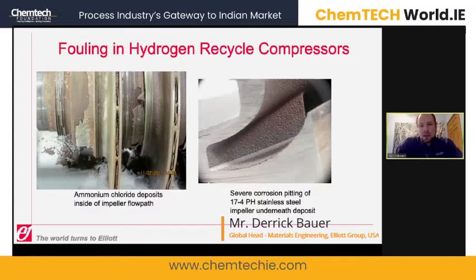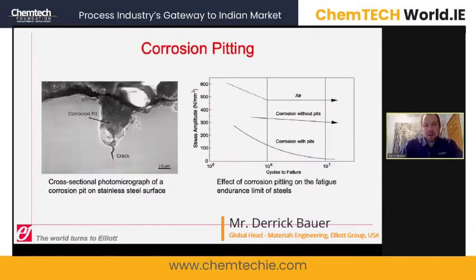In the case shown here, the deposit ended up causing corrosion pitting on the surface of the impeller. The impeller was 17-4 PH stainless steel, which has very good corrosion resistance in many environments. However, after cleaning off the ammonium chloride deposits, you can see the pitting of the surface of the impeller. And pitting corrosion is a very dangerous form of corrosion in any sort of rotating equipment.